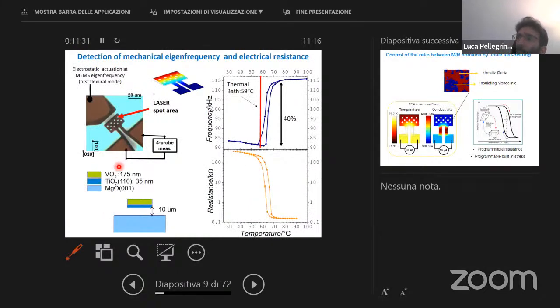So this is a MEMS. The black part here is freestanding, and this is the cantilever, where in the meantime we can study the conduction. It is made using a vanadium dioxide film with a titanium oxide buffer layer to allow the best growth conditions on an MgO substrate. Then, as said before, we fabricated the device, and this is a picture of the device from an optical microscope.